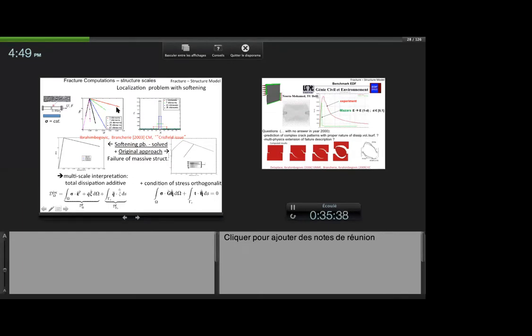Imagine you are here somewhere. So this element has a very large elastoplastic strain, and the others are unloading because they never reach sigma y. This element started at 0.99 sigma y. It immediately reduced the stress down to 0.98, 0.97, 0.96, and so on. And then the other elements remained elastic. And so basically, if you take now a finer mesh, this element, the one that is breaking, will be smaller and smaller, and all the others are elastic. And since it's smaller, you compute dissipation by integrating over the length of this element, you have smaller and smaller dissipation.